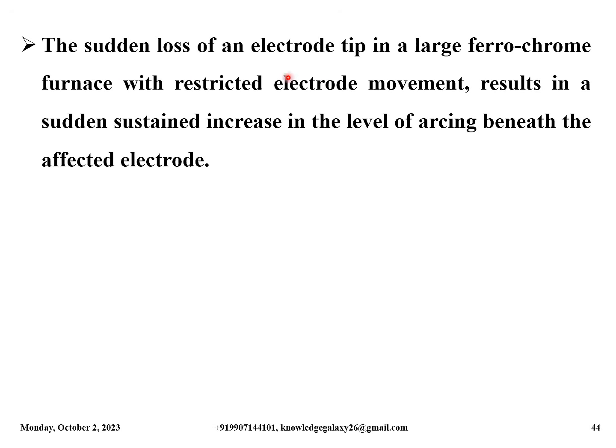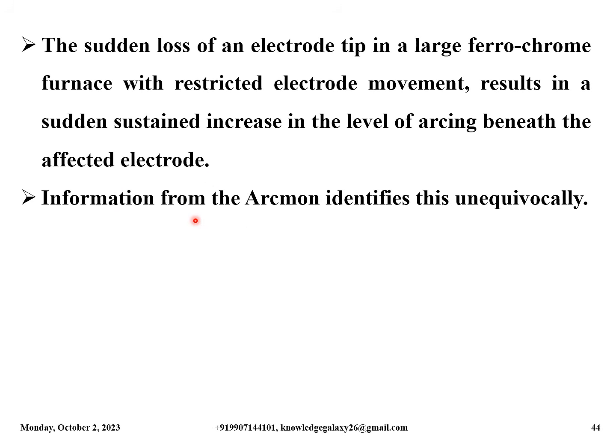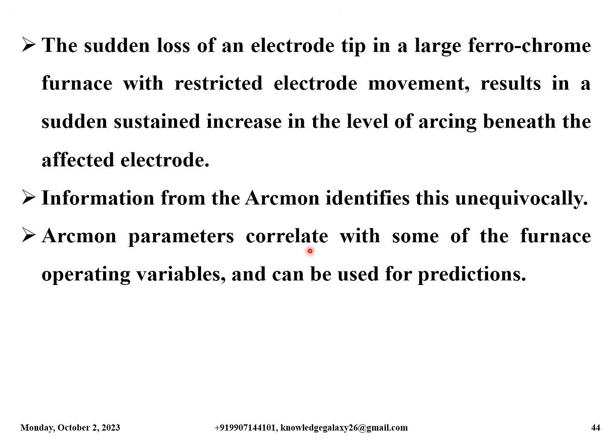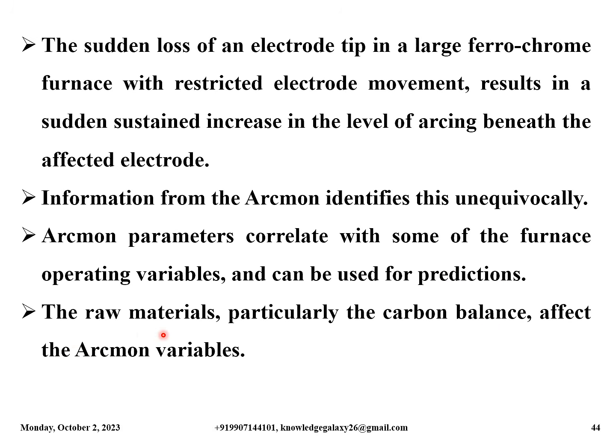The sudden loss of an electrode tip in a large ferrochrome furnace with restricted electrode movement results in a sudden, sustained increase in the level of arcing beneath the affected electrode. Information from the Arc-Mon identifies this unequivocally. Arc-Mon parameters correlate with some of the furnace operating variables and can be used for predictions. The raw materials, particularly the carbon balance, affect the Arc-Mon variable.